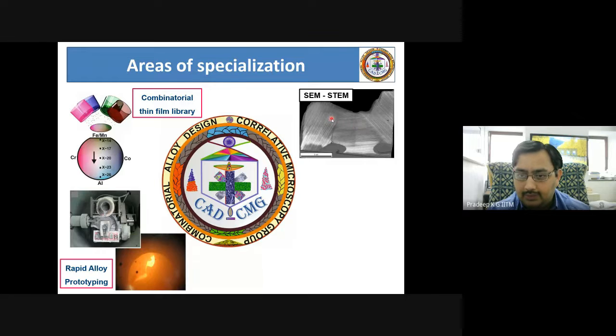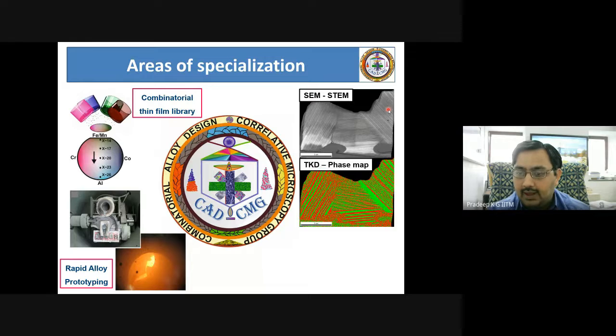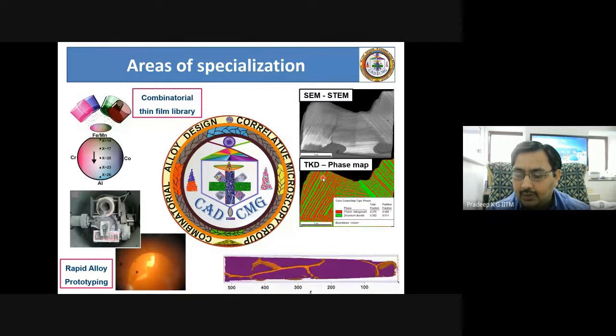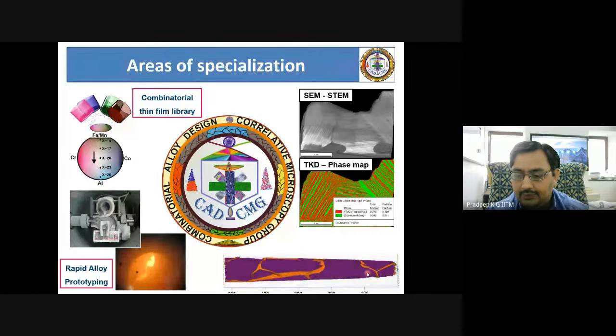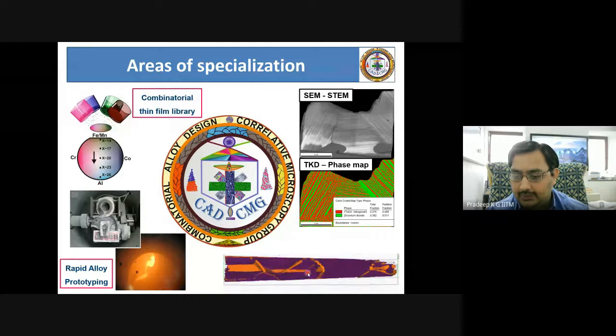And therefore, we develop techniques where the same region of interest or the same sample we characterize for their phase identification in terms of crystal structure by using a method called transmission Kikuchi diffraction, which I will present in the later part. And using the same technique, we can identify the orientation of the twins across this volume. And finally, from there, whichever region we are interested, we take to the atomic scale. And then this is the three-dimensional view of the same material, but using the chemical composition as the fingerprint and looking into what is called atom probe tomography.